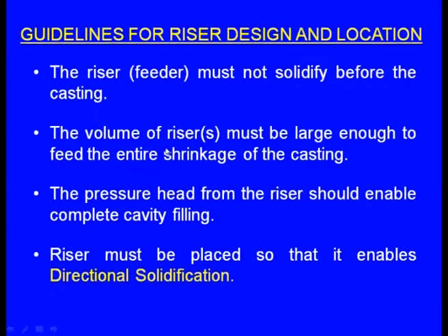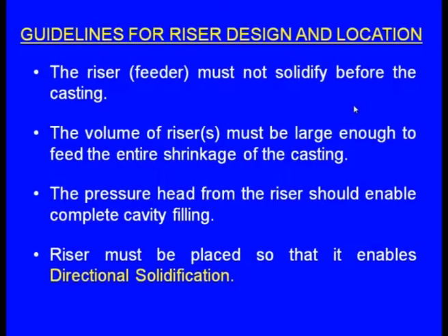Next, the volume of the riser must be large enough to feed the entire shrinkage of the casting. The first rule says that the riser must solidify after the casting solidifies. But here the riser is no doubt solidifying after the casting solidifies, but it is not large enough to feed the entire shrinkage of the casting. It is able to feed part of the shrinkage only during the initial stage of solidification, and at the final stage there is not sufficient liquid metal in the riser. Then how can it feed the casting? So, the quantity of liquid metal in the riser must be large enough to feed the entire shrinkage of the casting. That is the second guideline.